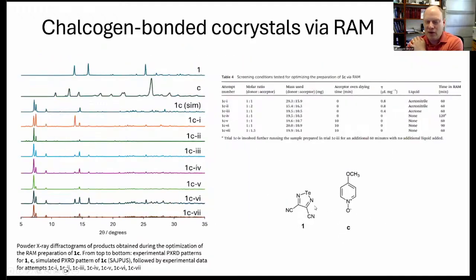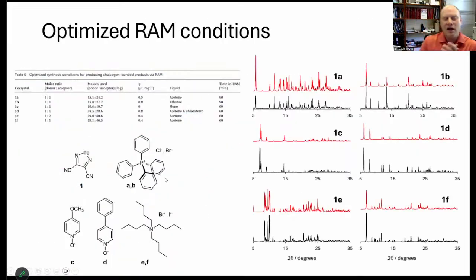Another example here with 1 and C. Again, here's what is simulated, what we expect from a single crystal study. And in this case, again, pretty convincing conversion. In most cases, there's some leftover impurities, but again, we can pick out the one here that gives us the best conversion, the best conditions. And this is just a summary of some of these optimized RAM conditions for these cocrystals.